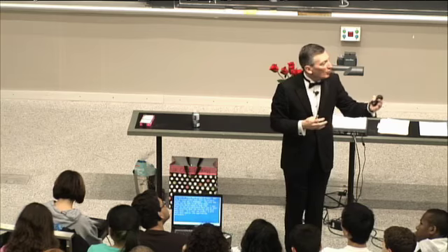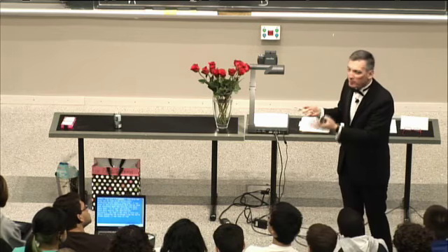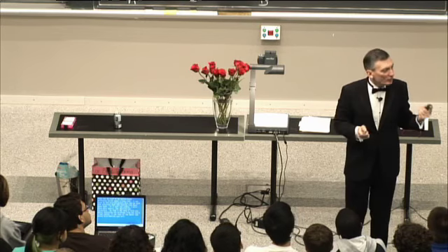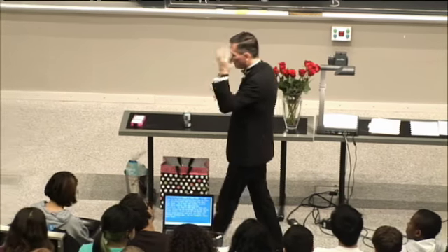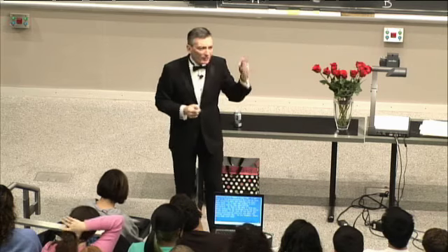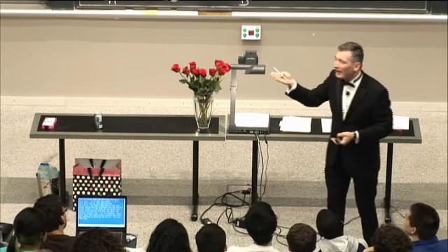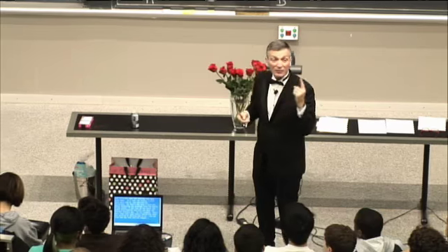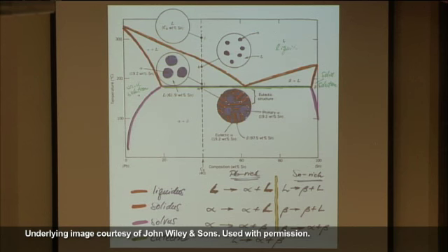And so that's why when I told you about, say, analyzing the wreckage from the World Trade Center, I can look at the metal and look at the phase distribution and tell you what the thermal history was. And so, for example, there were some cockeyed theories saying that the steel was burning. Somebody said that the steel melted and so on. You can look and you say that did not happen. Temperatures went fairly high, crossed into some different solid phases, went from BCC to FCC and then back, but didn't melt, because if it melted, we would have seen this kind of structure.